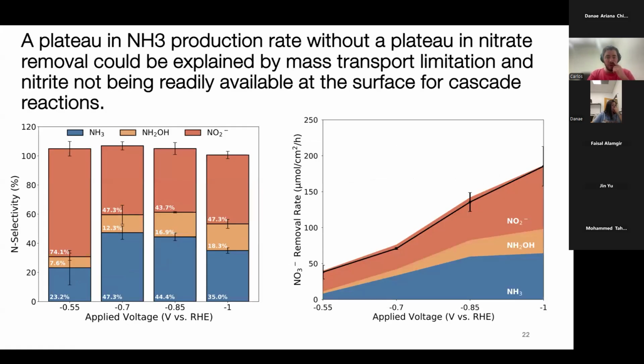And then we also look at where our nitrogen species are going. So we start with nitrate, and we have different pathways we can follow to different products. And we want to make sure we're accounting for our mass balance, and we're accounting where all of our nitrogen is going. So it is pretty similar in the way that at very low potentials, you have nitrite being the predominant species, and at very high potentials, there's a mix between nitrite and ammonia. And then it is important to note that hydroxylamine remains almost in the same order of magnitude across the full experimental range.